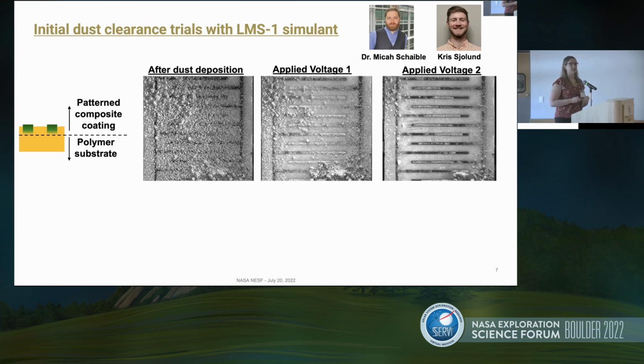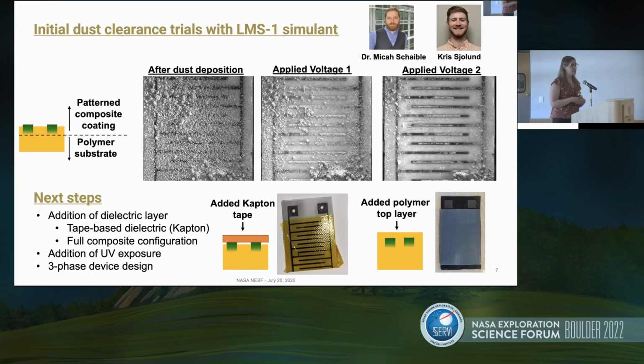But what we wanted to look at is how to get these things a little bit closer to the state of the art for traditionally manufactured EDS devices. So we've been working on some next steps that include the addition of a dielectric layer that will isolate the electrically conductive traces from the environment. We've tried two approaches. The tape-based Kapton is just single-sided Kapton tape stuck to the surface. And then we've also tried a full composite configuration in which we infiltrate the sprayed layer from both sides to make fully isolated and contained nanocomposite wires, which is, we think, the first example of that sort of device configuration that's been produced.